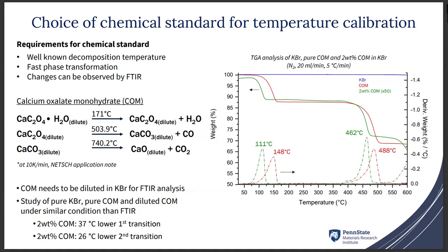The first step was to analyze those materials using TGA. We first analyzed the pure compound using parameters that we will use later on for the FTIR: nitrogen, a flow of 20 milliliters per minute, and a ramp of 5 degrees Celsius per minute.